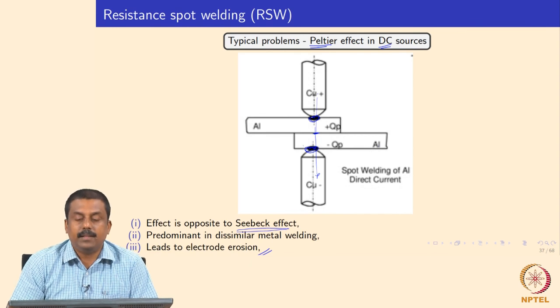To summarize: we looked at the mechanical properties of welds and plug ratios, then moved on to various problems associated with resistance spot welds — problems due to dissimilar thicknesses and dissimilar materials, and how to overcome them. We also covered design aspects such as the minimum distance between two electrodes to avoid the shunt effect, and why direct current should be avoided — particularly for dissimilar materials — in favor of alternating current due to the Peltier effect.